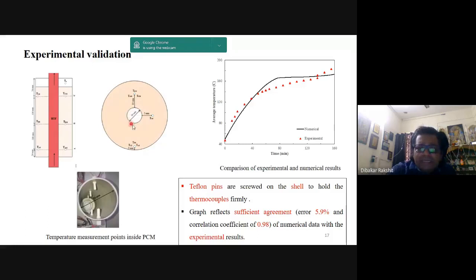So basically this is the point through which the hot air was blown, and these pink colored points are those through which the phase change material was stuffed in. You can see that after we started the experiment, we found how much time it takes, and what the temperature variation is with time, and how it is reaching the asymptotic limit. So for that we compared it with the numerical data. I will be discussing the CFD which we have done.